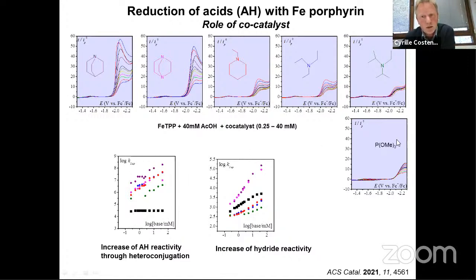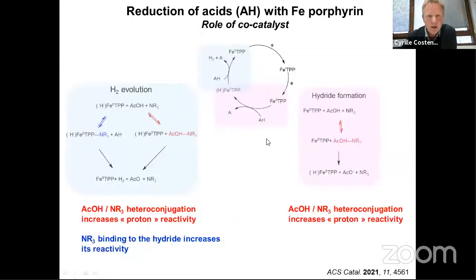And then we did compare with the addition of a co-catalyst, which is not a base, but a phosphine, which is not a base, but can bind the iron in iron porphyrin. And what you observe is that with this co-catalyst, you get an increase of the catalytic current also, but no shift of the wave, which means that you only modify K2, the reactivity of the hydride. So here is the proposition to explain what's going on. For the formation of the hydride, the more important effect is actually the heteroconjugation of the acid with the added base, which increases the reactivity of the proton. Then, once you have formed the hydride, you get also an acceleration due to the more reactivity of the heteroconjugation between the acid and the base.